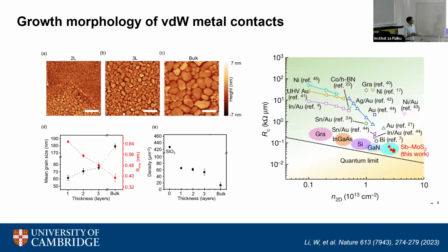And the other key point was that as soon as this work was published, many groups started to make van der Waals contacts with other materials as well. One of the key works that got published was on bismuth, from Jing Kong's group at MIT and some people at TSMC, which showed this plot of contact resistance versus the carrier density of various metals. And indium gold was somewhere around here. So you can see that it's not the lowest contact resistance.